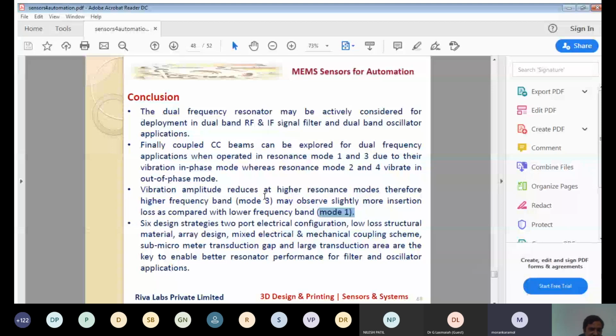Then the 6 design strategies that I have discussed previously. First, a sub-micrometer transduction gap. As I told you, the sub-micrometer transduction gap was a 387 nanometer gap. And a large transduction area: instead of having a single beam, we had 4 different beams, so the transduction area was very large. And the electrical configuration, coupling scheme, mechanical configuration, and array design, everything in the strategy that we applied was very successful.